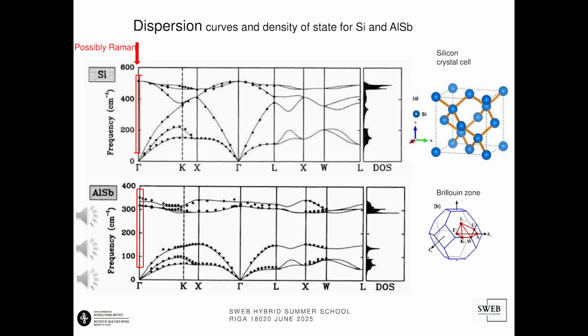In the case of real crystals, vibrational waves propagate in 3-dimensional space. These directions are characterized by the Brillouin zone. The slide shows the crystal lattice structure and Brillouin zone of silicon. The slide also shows the dispersion curves of vibrations in different symmetric directions of the Brillouin zone. Each wave vector has 3n vibrations.